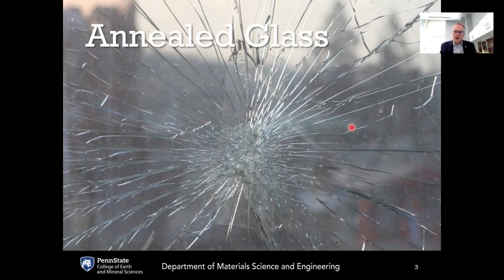But that glass product could have experienced differential cooling as a result of being shaped in that form. In other words, the exterior part of the glass could have cooled faster compared to the interior part, which could lead to the development of stresses that are retained in that glass product after it has been formed. Now, if those stresses are not carefully controlled, they can lead to the glass product being weak or having weak points in it where it is easily broken.